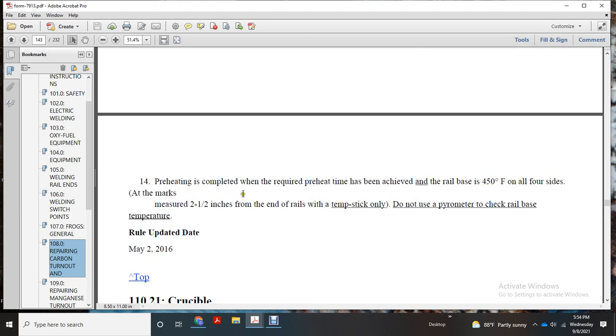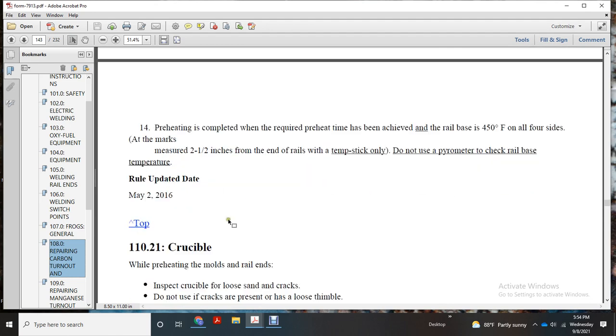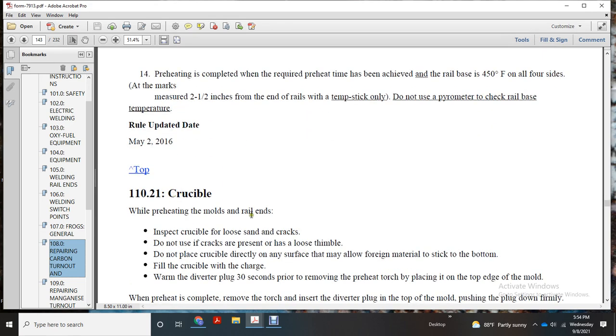four sides, measured 2.5 inches from the end of the rail base with a temp stick. Do not use the pyrometer to check the rail base temperature. Crucible: when preheating the mold of the rail end, inspect the crucible for loose sand and cracks. Do not use if cracks are present or the thimble is loose. Do not place the crucible directly on any surface, to keep foreign material from sticking at the bottom. Fill the crucible with charge and warm the diverter plug 30 seconds prior to removing the preheat torch.